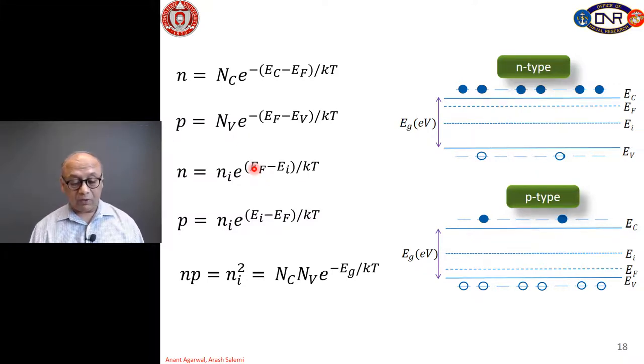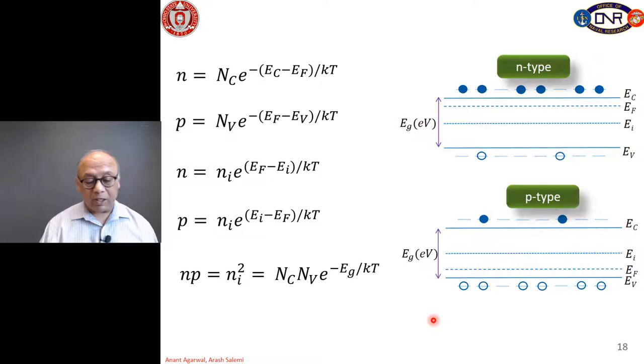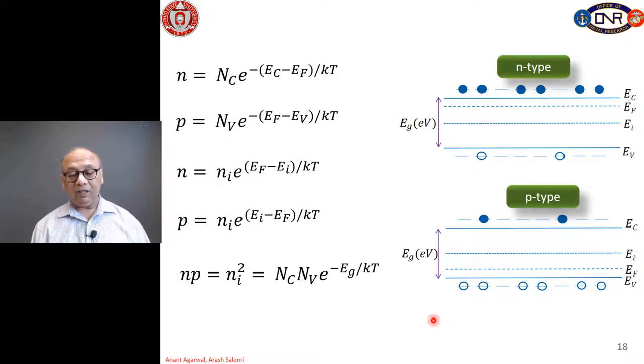And the product of the electron and hole concentrations is equal to ni squared, which is a constant for a given material, because Nc is the effective density of states in the conduction band and Nv is the effective density of states in the valence band, which are different for different materials but constant for a given material. These are effective density of states, as if all the states were at the bottom of the conduction band edge or at the top of the valence band edge. And again, the band gap is a constant for a material. The only variable here is temperature. So if we increase the temperature, you can see ni increases very rapidly.